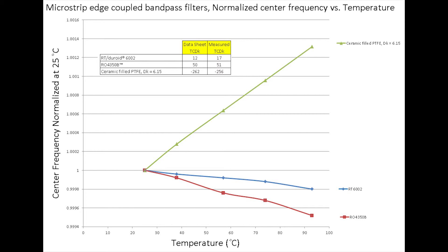Another example of this in relation to microwave performance is a chart shown here. This chart is part of a microwave circuit — a bandpass filter that is edge-coupled and microstrip. These filters were all built to have a center frequency right around 2 GHz, made on three different materials. One material is a PTFE material with a relatively higher dielectric constant of about 6.15. The other materials are the RT/Duroid 6002, which has a lower dielectric constant around 2.94, and then the Rogers 4350B with a dielectric constant of about 3.66. These circuits were subjected to a range of temperatures and the shift in frequency was recorded and back-calculated to determine what that means for TCDK.